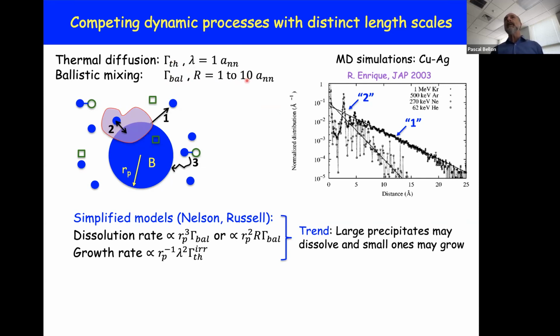The main way that we know about this distribution of relocation distances is from molecular dynamics simulations. Here's an example of the histogram of relocation distances. This is a normalized histogram as a function of distance, in a semi-log plot. What you see is that for various irradiation conditions in this copper-silver alloy, we see an exponential tail of mixing. This medium range mixing is very unique to irradiation. And there is a little bit of short range mixing too, jumps from one location to a nearest neighbor site. This is the process labeled number 2.